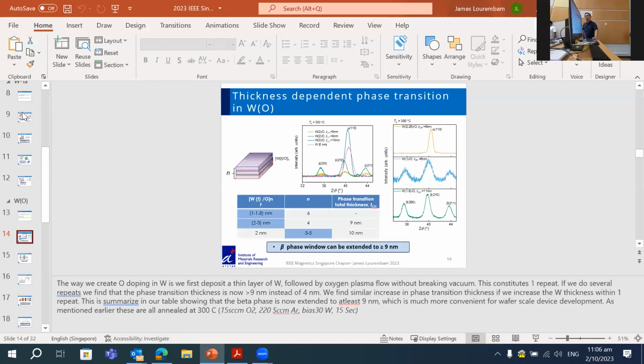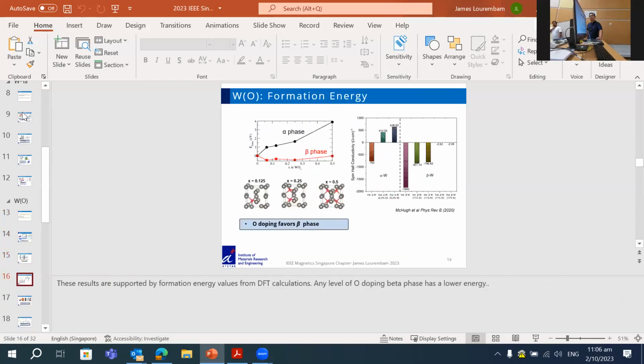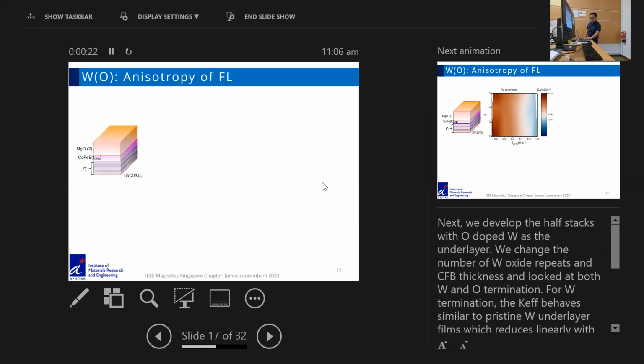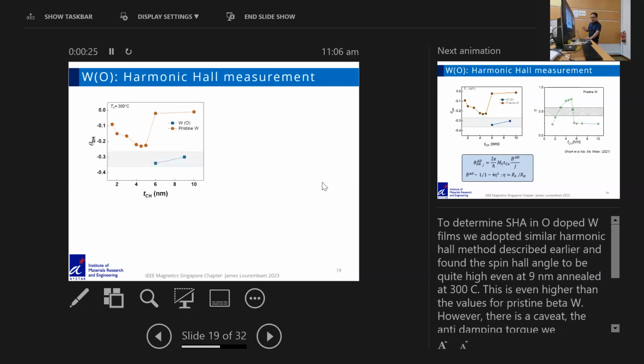Yeah. So this is actually a theoretical calculation, right? So here, yeah, I will get in. This is a very good question actually. So this theoretical calculation shows that in a very pristine beta tungsten, the spin Hall is the highest. And once you introduce oxygen, it will go down. And if you increase more, it will go down even further. So what we wanted to do is introduce only a tiny bit of oxygen, which is what we've done experimentally.